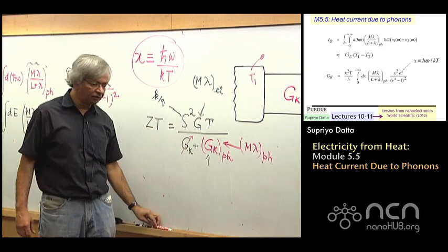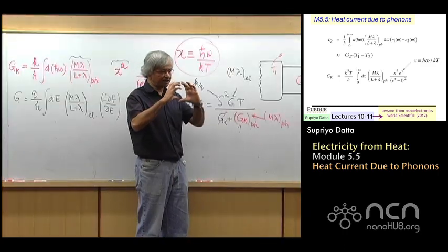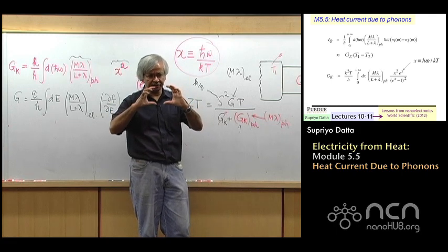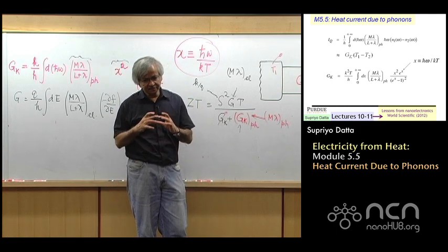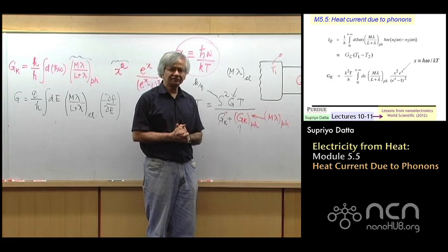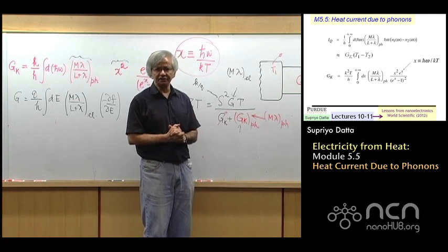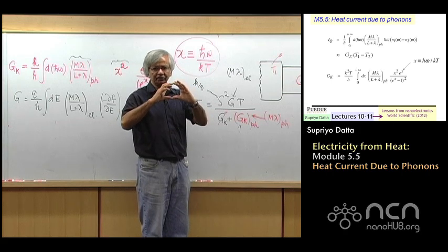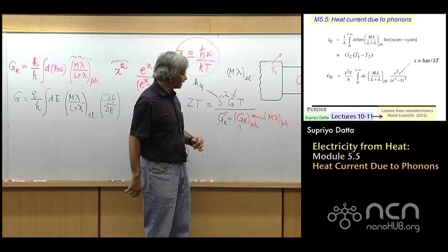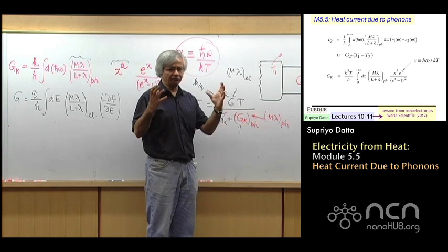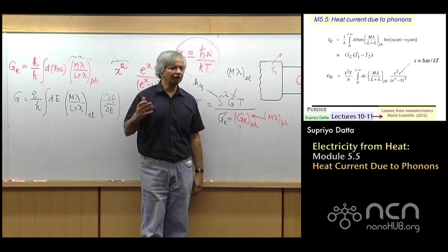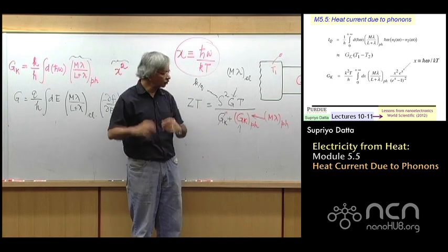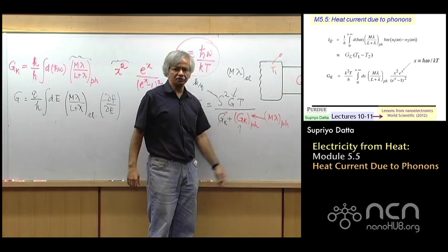Often in these good thermoelectrics, in a given cross-section, the number of modes is this idea of how many wavelengths fit into the cross-section. And the semiconductors typically have a wavelength of 10 nanometers to 100 nanometers. So how many wavelengths fit in? You get a relatively small number. By contrast, if you look at the phonon wavelength, there you are often talking of 1 nanometer, something much smaller, which means for a given cross-section, you usually have a lot more modes.